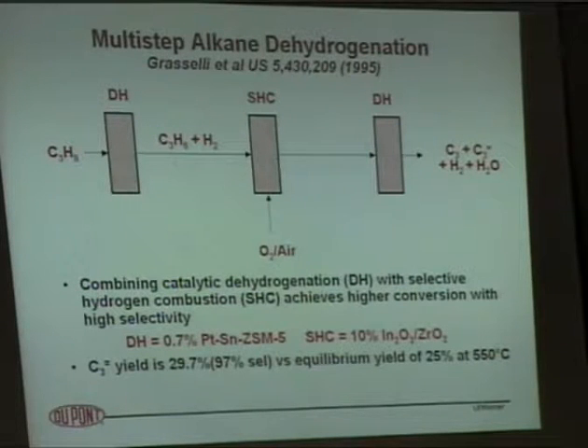His next approach in the same patent was to combine both catalysts into a single reactor. So as you're doing the dehydrogenation, the oxidation catalyst will selectively oxidize only the hydrogen, not touch the propylene or the propane. So combined these two catalyst systems in a single reactor, and found that he could get 48% yield now to propylene versus the 20% equilibrium yield under the conditions he reported.